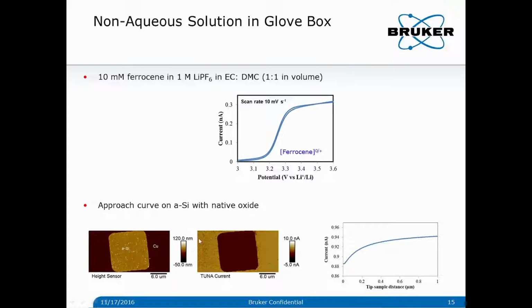And here is a conductive AFM image of a silicon anode pattern on a copper current collector. This measurement was done using the SECM nanoelectrode probe as a conductive AFM probe, inside a glovebox, in a dry environment, no liquid here. I just want to show you that on an amorphous silicon surface, because of the native oxide, you won't see any electrical current there. We know this oxide surface is inactive.